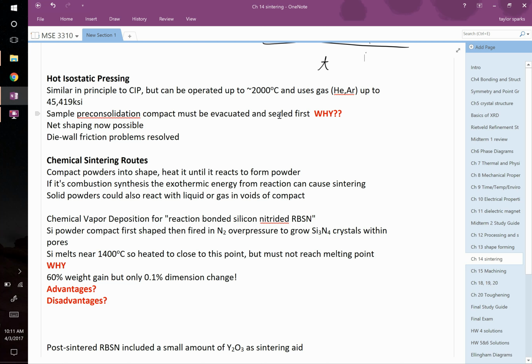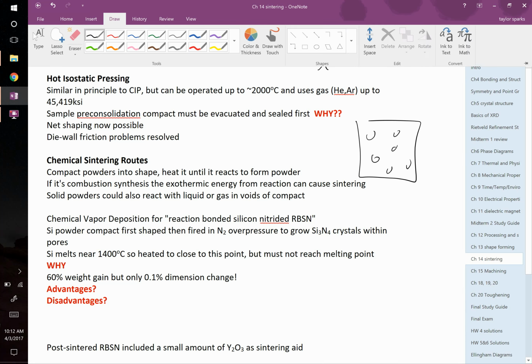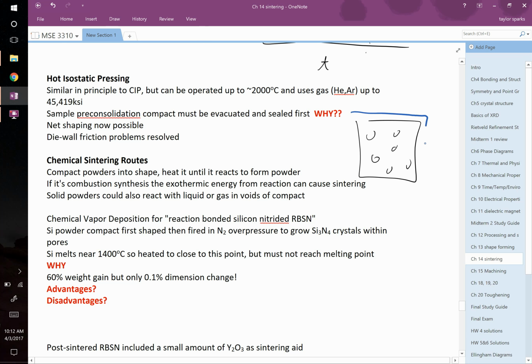Yeah, basically you want your sample to look like this, right? You've got the ceramic that you want to sinter, and it's got pores and whatever, that you're going to try and densify. You have to put around it this gas impermeable layer such that if you have a really high pressure here, you still just have pressure at atmosphere inside of here, right? So you have a pressure differential. That's what causes the isostatic pressure on this thing.